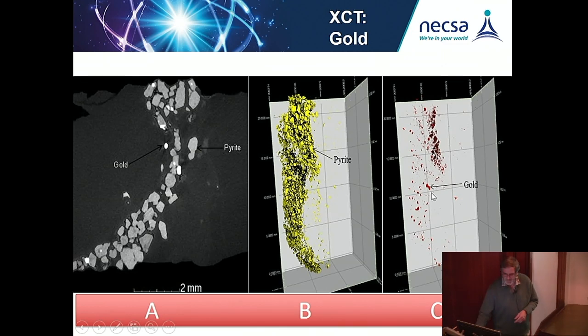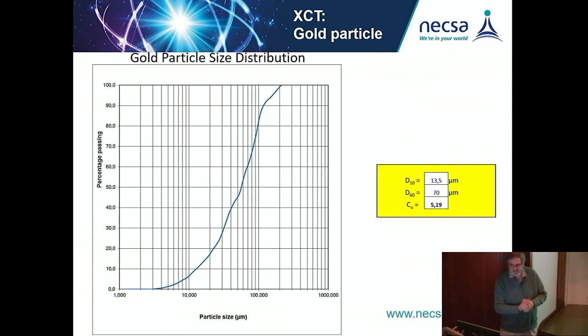Here you can see the gold, and this is work from Glenn Nwala, who did his MSc at Necsa, and is currently employed by Wits, where you have your sample, but then in 3D you have your pyrite together with your gold. With your voxel change, or the minimizing of the voxels for the pyrite, you end up with your gold particles in that sample, and also a volumetric determination of the size distribution of those particles, the particle size distribution of the gold in 3D.